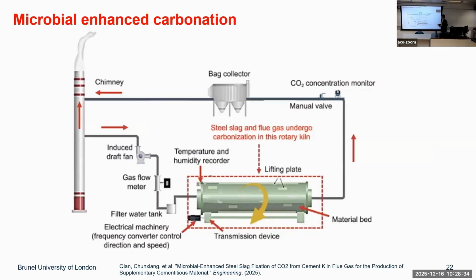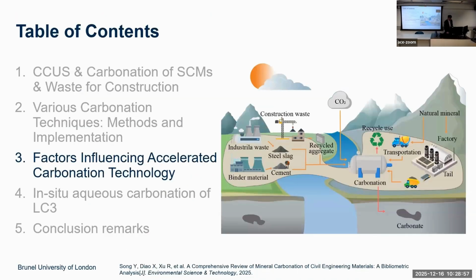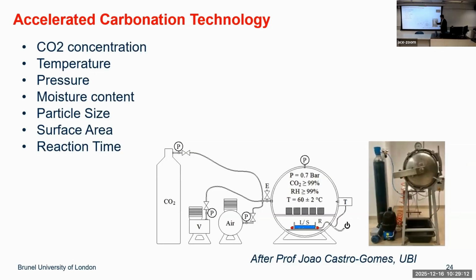There are other ways to improve carbonation, because at the moment the carbonation efficiency is around 15%, maximum 25%. Some people use bacteria to improve carbonation, such as work done by Xiangming from Southeast University. As I mentioned, the most promising way in my opinion, which could be scaled up, is so-called accelerated carbonation with wet and dry carbonation technology. This is my research partner from the University of Beira Interior in Portugal.